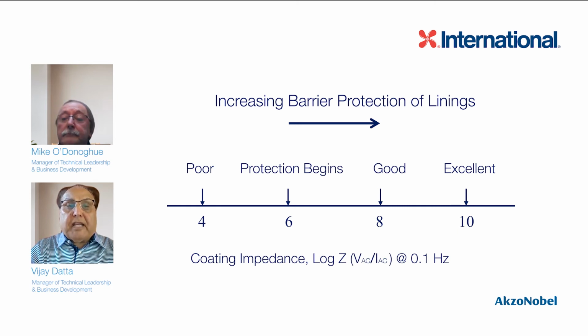Now, I mentioned about the EIS, which is electrochemical impedance spectroscopy. What that determines is the barrier properties of the lining. Now, what we do is we determine the impedance as a function of frequency. And when the readings are high, like a 10 or 11, that means the coating is going to give us a very good barrier protection. As the EIS value decreases, then you don't get a good barrier protection. As you can see here in the graph, the protection begins at 6, but that's not very good. So we try to shoot around 9, 10, and 11.